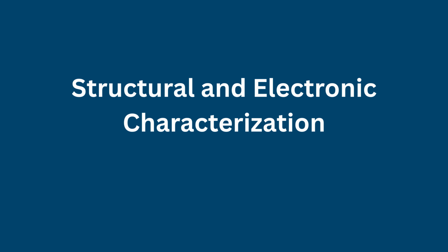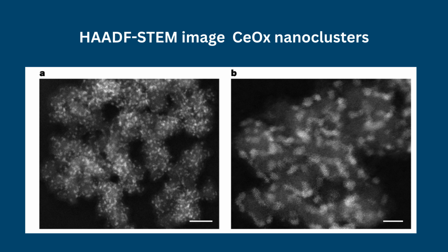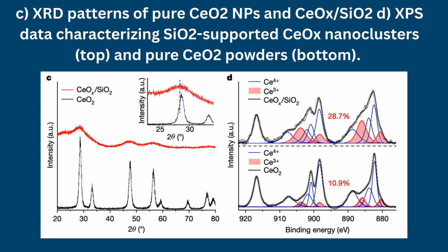Structural and electronic characterization. Advanced characterization techniques confirm the structure and dispersion of the catalysts. HAADF-STEM imaging reveals uniformly distributed cerium oxide nanoclusters on mesoporous SiO2. X-ray diffraction, XRD, indicates ultra-small crystalline domains with fluorite structure and lattice distortion. Raman spectroscopy identifies oxygen vacancies and structural defects. X-ray photoelectron spectroscopy, XPS, shows a high fraction of Ce3+ species, corresponding to enhanced anchoring capacity.